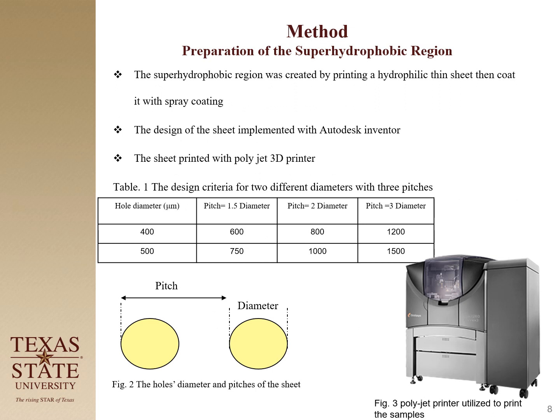So how I did that: I designed in Inventor thin sheets, about 100 microns in thickness, and I made holes in them. I'm trying to create an array of those holes, 4 by 4, with the diameter varying from 400 to 500 microns, with 3 different pitches for each diameter. I printed using a 3D printer, a PolyJet printer.